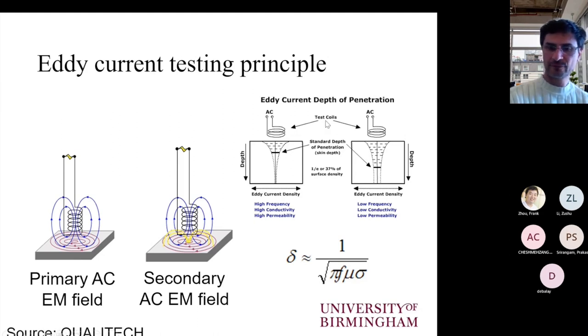And this can be visualized also on the right-hand side set of schematic diagrams, where you can see that high frequency, high conductivity, high permeability restricts the depth of the eddy currents. In the case of lower frequency, lower conductivity, lower permeability, the depth is increasing accordingly. This empirical equation can be used to evaluate what kind of frequency we need to apply for a particular inspection, or it can be taken into account in order to enable us to ensure that we know which part of the test piece we have actually inspected.